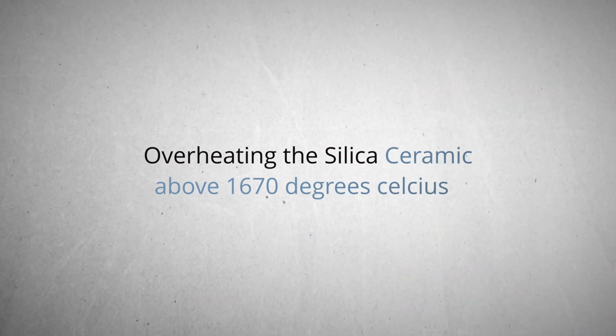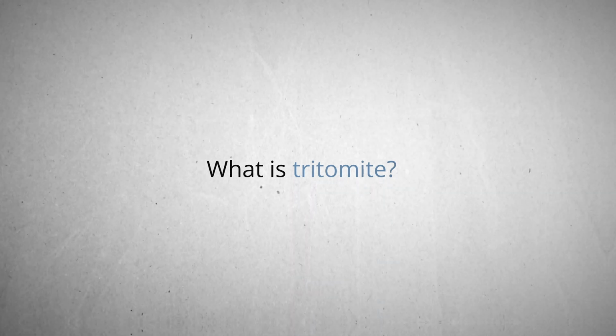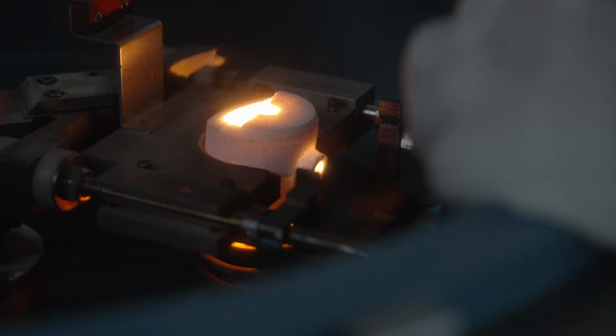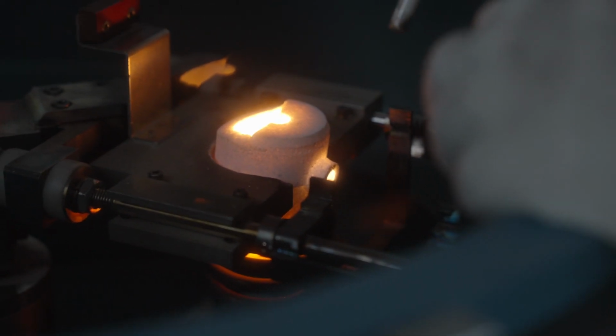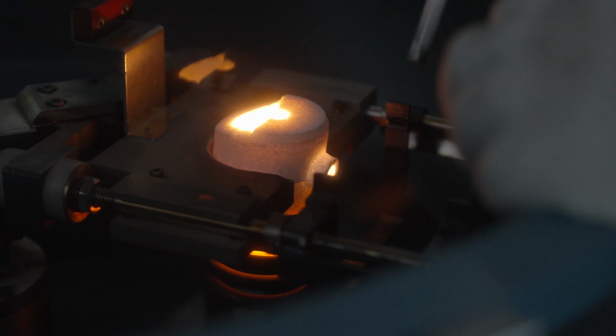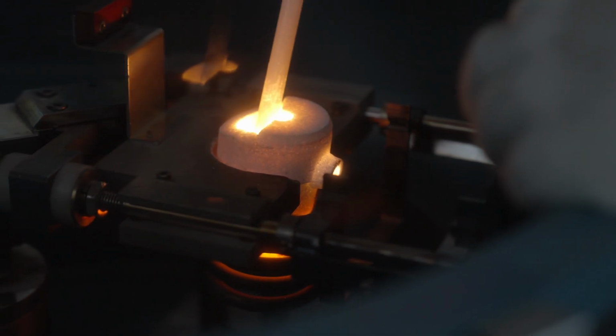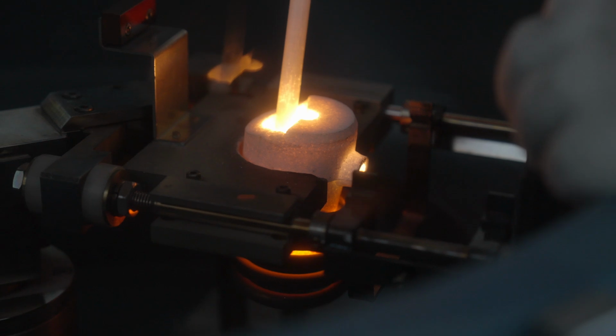Now I know that the overheating of silica ceramic above 1670 Celsius, which is much lower than most platinum alloys' melting point, can cause the melting of tridymite. What is tridymite? Tridymite is the unique crystalline form of silica refractory, so basically it's referring to the crucible that we're using for casting. That actually melts at 1670. So when the crucible gets softened, when it goes above that temperature, it causes the dissolution of the silicon into the metal content. And hence, that's how we're getting silicon contamination.